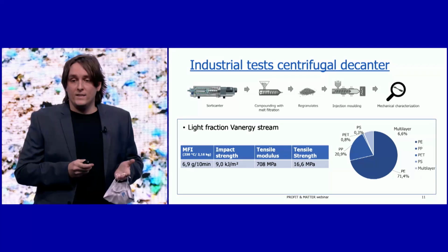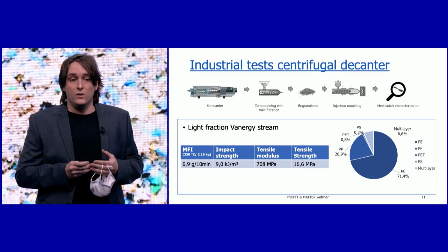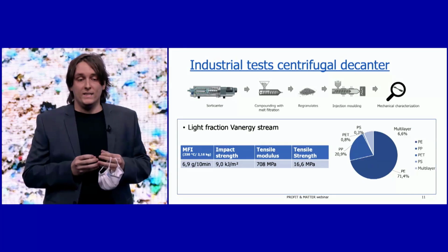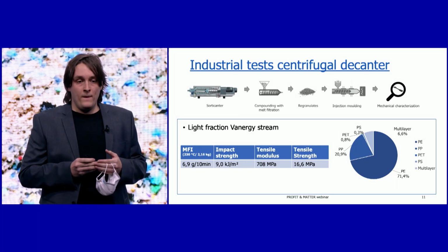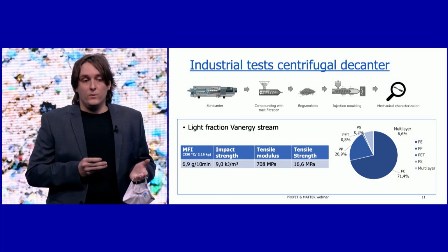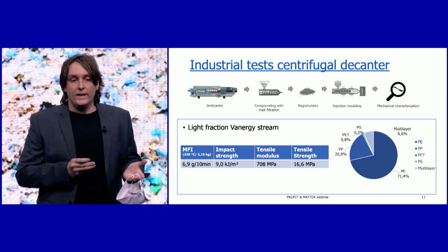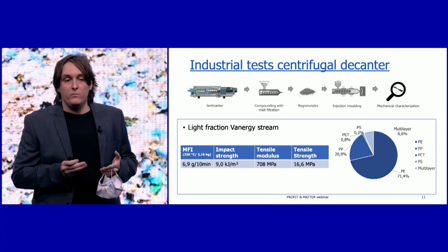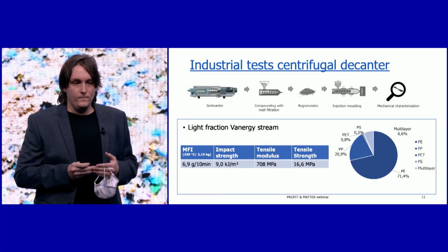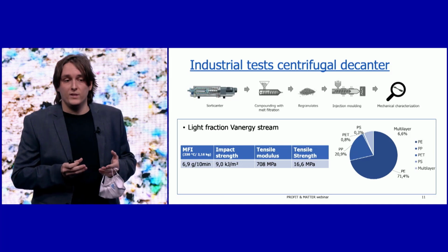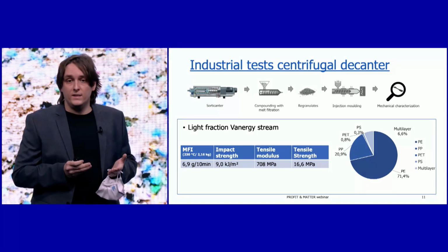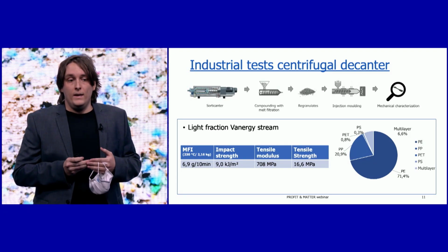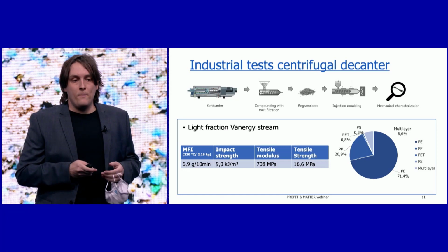Then the light fraction of the Vanergy stream showed a good composition and has a high polyolefin content. After separation with the centrifugal decanter, most of the heavy polymers were removed. Then the stream was processed on a lab scale, and the properties were determined, and they showed good properties.